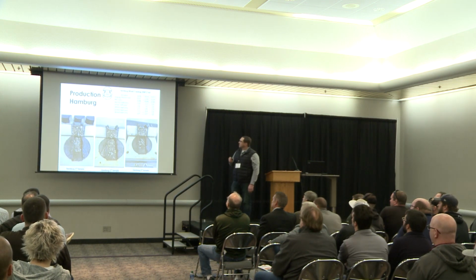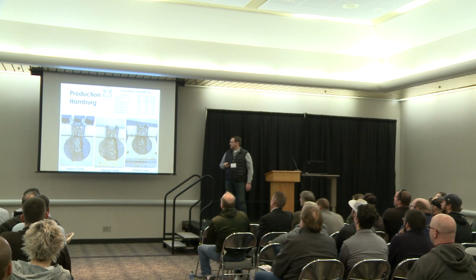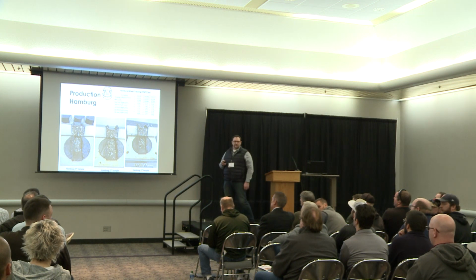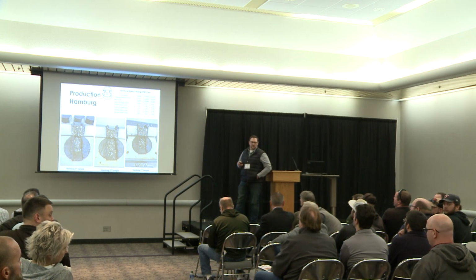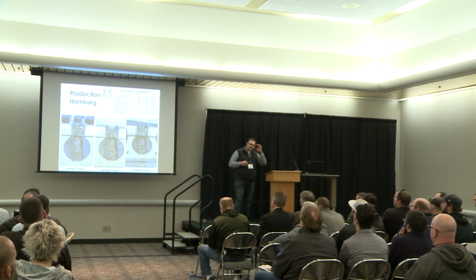Production Homburg, we can see here we ran it out 20,000 passes. Pretty similar, 6.4, 6.3, 6.8. Anything to add to that, Bobby? Yep, so it's going to be stiffer.